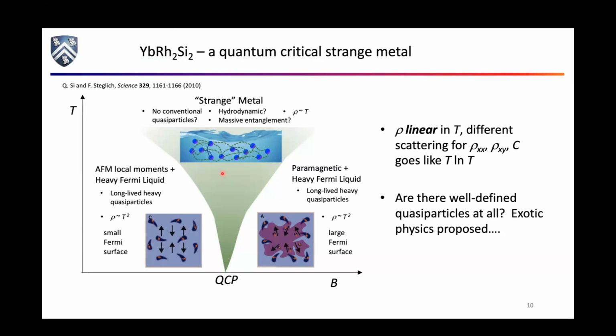And it's an interesting question, how well defined are quasiparticles? Just for reference, all the experiments I'm going to describe to you are being done at temperatures warm enough where this quantum critical fan just spans all available magnetic field space that you can get to in the lab. So everywhere we're going to look in our measurements, we're going to look from 3 Kelvin and up. The whole region is not Fermi liquid. The whole region has rho linear in T. A thing we would like to do, of course, is to do measurements like I'm going to describe at lower temperatures, where you can try and field tune across the different regimes. That's very exciting, and I'll talk more about that.